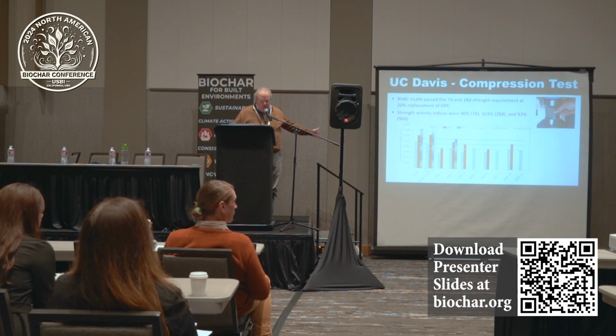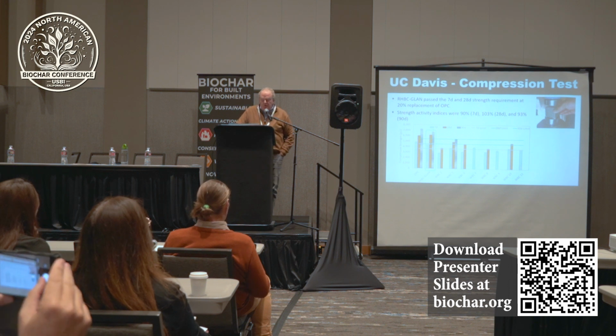Again, stealing a little from the next presenter, Samaya, looking at the same sort of data in a slightly different way. What you see here is the ordinary Portland cement on the far left of the slide. These are the 7-day, 28-day, and 90-day studies. The rice hull biochar, and this, by the way, is at a 20% replacement, shows similar compression strengths in their formula to ordinary Portland cement. Compared to some of the other biochars out there, again, similar. Some of them perform better, some perform less.